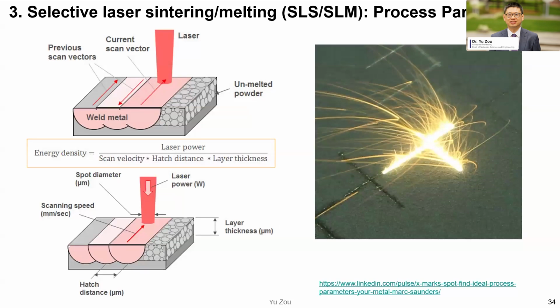Okay, so in this process, typically there are a few important parameters we need to optimize and control. For example, a key parameter is called the laser energy density, which is related to laser power, how much laser power you use, and scanning velocity, hatch spacing, which is the distance between each scan line, and also layer thickness. So to make a good part with a high density, you really need to optimize these parameters to make a relatively dense part.